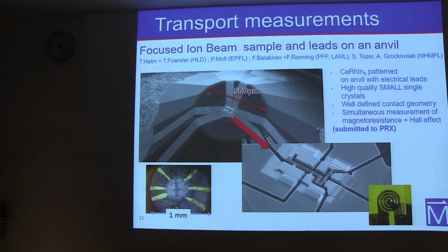So the advantage is that we have well-defined contact geometry. Here you can see that we measure several axes of the same crystal, the A-axis and the B-axis, but you can also measure transport and Hall effect simultaneously in the sample. Looking at this picture, we see that the leads go on the anvil instead of going through the gasket. So when we apply pressure, the gasket on top does not destroy those leads, which makes it really robust. For me, it's the future for high pressure transport.